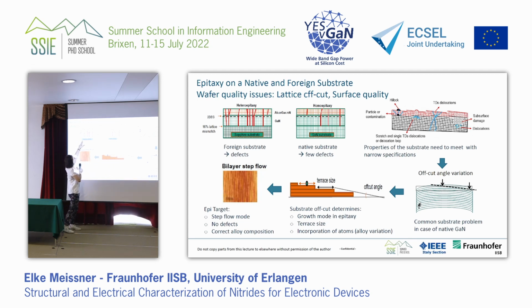And this depicts the heteroepitaxy case and the homoepitaxy case. So you see, this is no off-cut also in this simple pictogram. And you say in homoepitaxy, we only take over things that come from the substrate. And in heteroepitaxy case, we create a lot of defects at the interface. Now what can happen if we do epitaxy? The lattices are being inclined a little bit. We create a step flow growth mode, and then there can be something that happens during the epitaxy of the substrate.